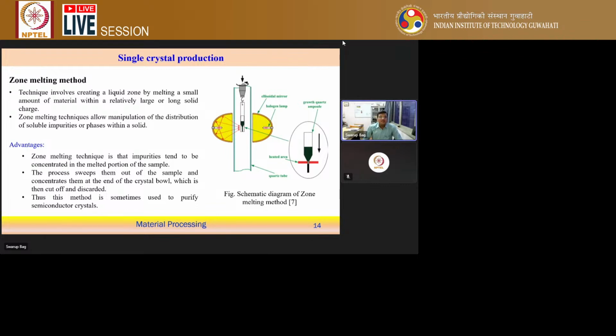So what happens in this case, when we melt a very specific zone, is that it allows manipulation of the distribution of any impurities or phases within the solid. When you're melting it, the impurities will segregate. Usually the lighter impurities come to the top surface, and heavier impurities go to the bottom surface. So basically we are collecting the impurities by melting in a very localized position, a particular zone, and we keep gradually moving, collecting the impurities present there. And of course, at the same time, we follow the solidification in a particular direction. Then we can produce the single crystal structure. This is the simplest way to produce it, and it is called the zone melting method.